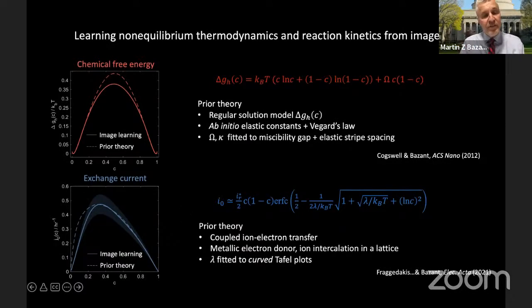And as I said, this is something that I think could not be measured any other way, because I showed you the system is incredibly heterogeneous. All the different concentrations are evolving at the same time. So there's no way macroscopically to just measure current voltage and try to infer the reaction kinetics. There's no way to get it. You have to look inside the system and just deal with that heterogeneity. And amazingly, it comes close to this theory.